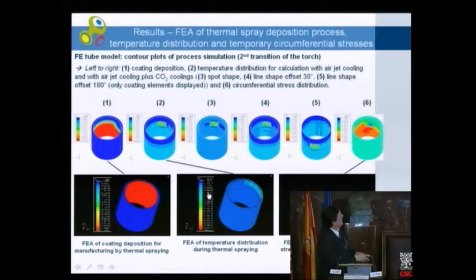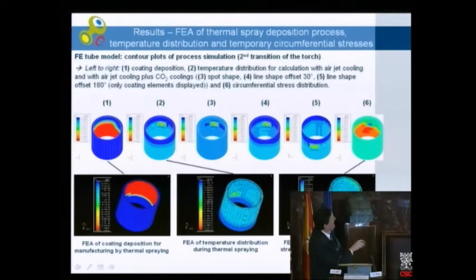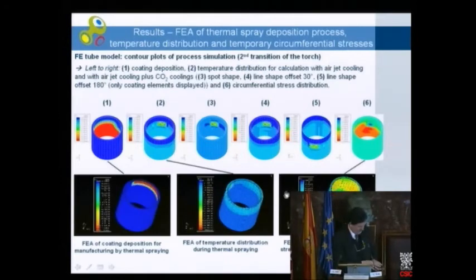And in the second, we show the temperature distribution. You see the hot spot, which is just occurring on the surface, a spiralic geometry, but the material itself is not overheated. And on the right-hand side, we had the heat transfer, the temperature evolution, and now we have the stress evolution. And you see there is a quick relaxation when the hot spot is traveling over the internal surface of the cylinder. So these were the first steps in understanding this process.